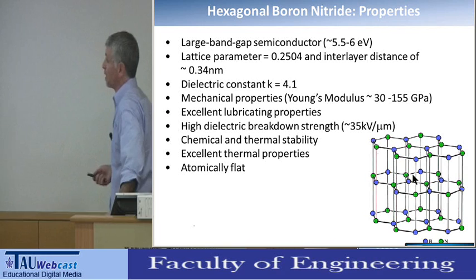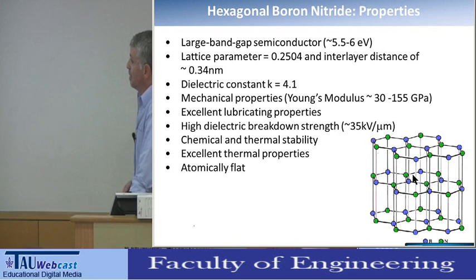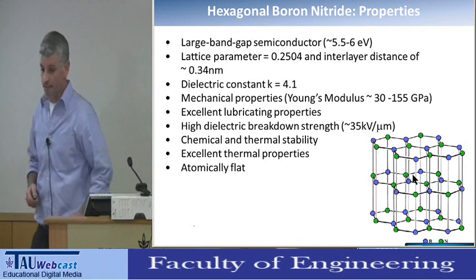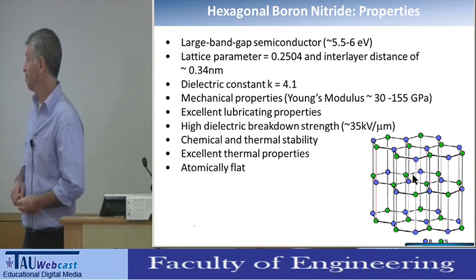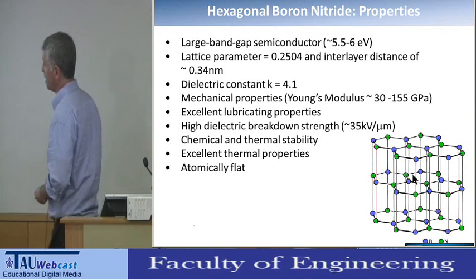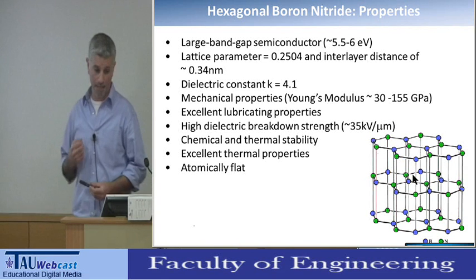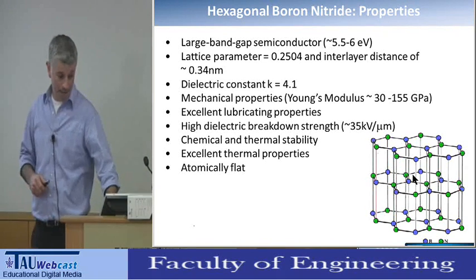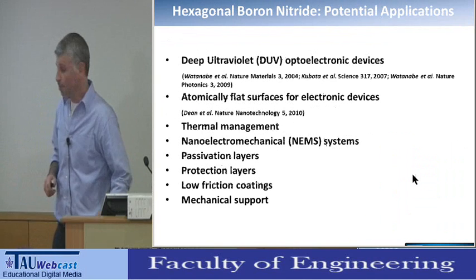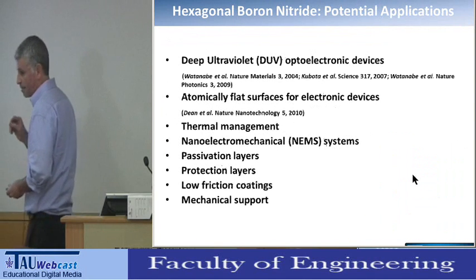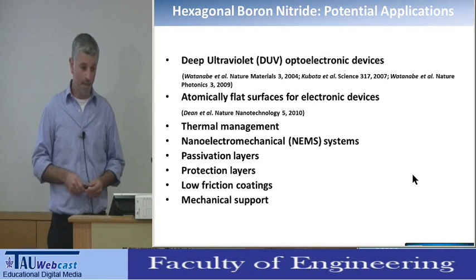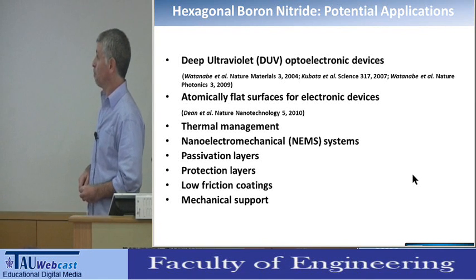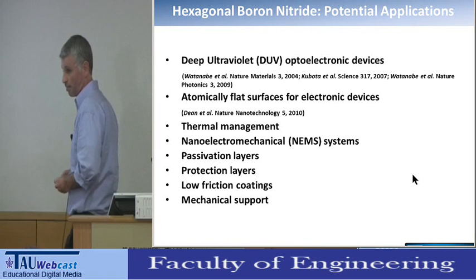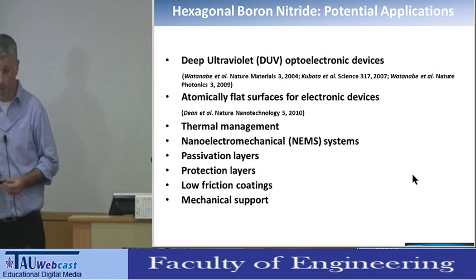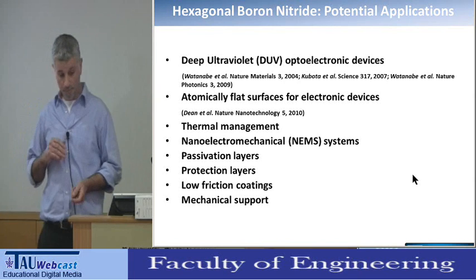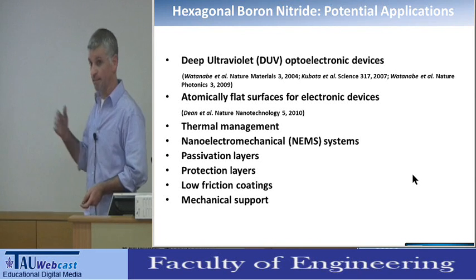It is a wide band gap semiconductor that has very nice and good mechanical and thermal properties, a very good thermal conductor. And it's very chemically and thermally stable, and is atomically flat. And this is very important for electronic devices in the nanoscale, it turns out. And specifically, it was shown that when you make devices with graphene on top of hexagonal boron nitride, both of high quality, you can get enhanced mobilities in graphene.